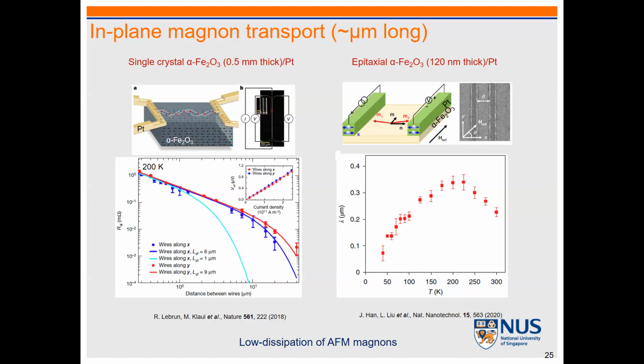As some preliminary study by other people using anti-ferromagnetic transport, most people study in-plane propagation. Most of them use alpha-phase iron oxide, hematite. The Mathias Kläui group found that spin current can propagate micrometer scale, very long, because it's a single crystal. The Ross group at MIT also found it can go to hundreds of nanometers, using 120 nanometer thick iron oxide. Both reported quite low dissipation. But these are all in-plane measurements, where you can extract interesting spin-related parameters, like spin diffusion length. But actually, in a real device, it's not very useful.